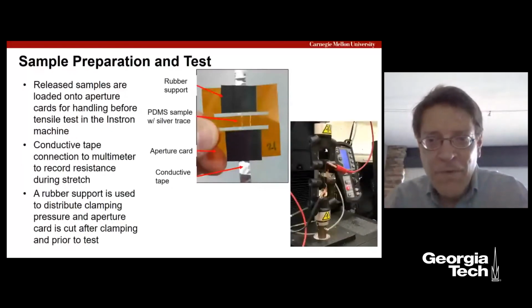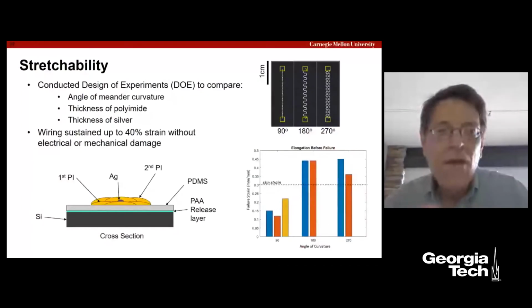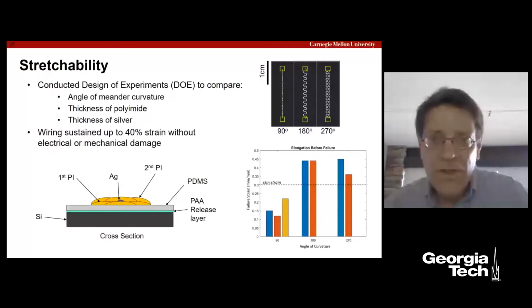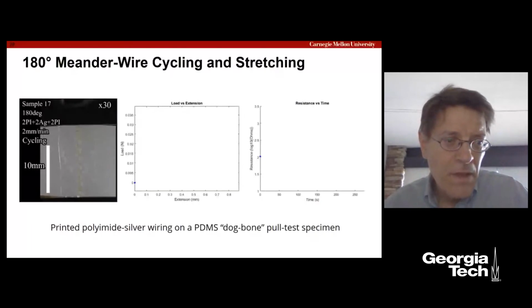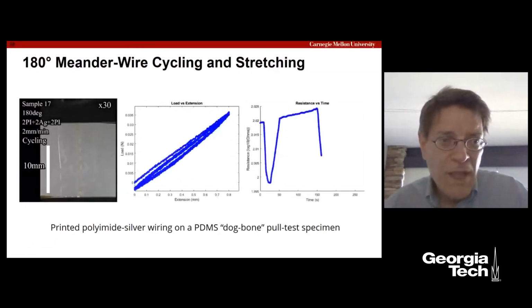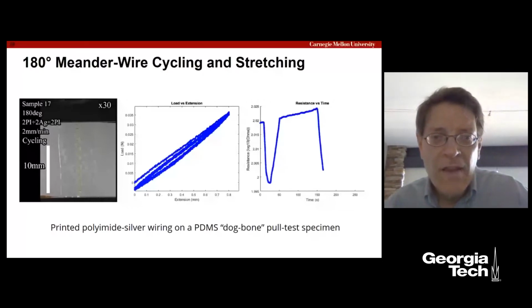And then we found, when we're doing these Instron tests, we had to figure out how to do the sample prep. So we created rigs to be able to handle these things, which are, if you think about it, sub-millimeter. It's like handling cellophane, and there's a danger of them sticking together. So we did some preliminary stretching experiments with this polyimide wiring, and this has been done in John Rogers' group and other groups. There's a lot of groups that work on these, and we simply wanted to have our own baseline information on this, and finding that here we have this PDMS with this meander wiring of polyimide and silver, and in fact, we're able to get stretch.